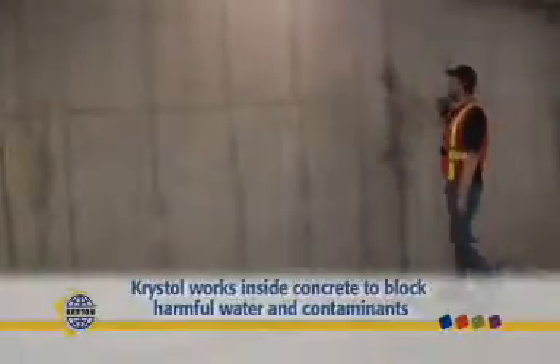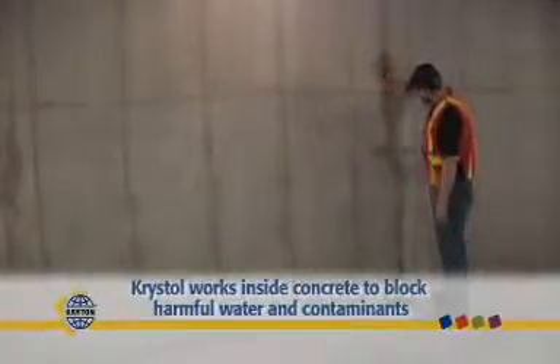Since the majority of active crystalline chemicals migrate into the concrete within the first 28 days, the surface-applied slurry can be completely removed from the surface after this time with no impact on its waterproofing properties. To apply the surface treatment, you must first prepare the substrate.